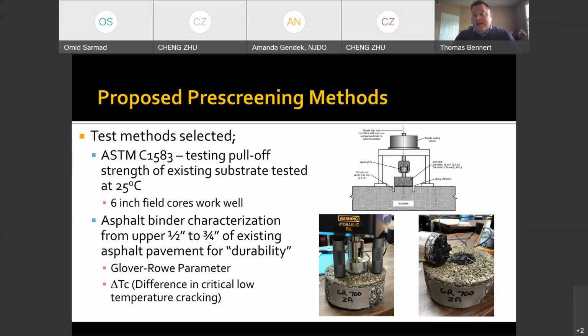The other thing that we want to take a look at is, okay, well, pull-off strength tells us one thing, but we can still have high stiffness, but materials that are highly aged. And so we're also looking at the asphalt binder properties in the top half inch of the material to get an idea of the durability of that asphalt binder.